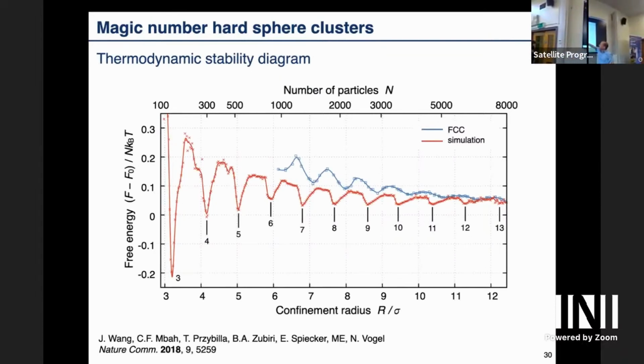But at the end, from the simulation, you see here, this is sort of the free energy offset, some background. Again, this would probably take quite a bit of time to explain, but if you're interested, I can explain it to you separately. It shows us sort of the relative stability as we change the size of the cluster. And we see for some radii, for some sizes, so here's the number of particles, and it's connected to the radii because this is a 53% density, so constant volume. So we see for certain radii, it's more stable, free energy is lower. And for other radii, it's less stable, the free energy is higher.